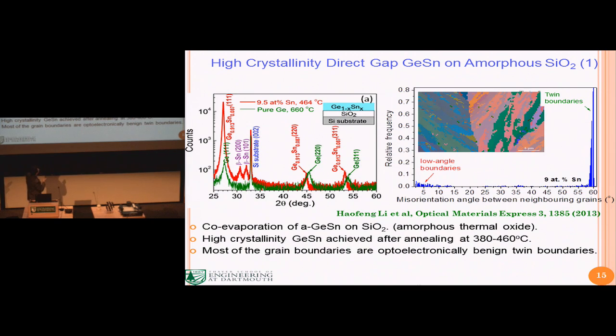And we also did some analysis of the grains. So this is basically using electron backscatter diffraction. Each of these different colors of pieces means an individual grain. The scale bar here is about 5 microns. You can see you can get grain sizes about 10 microns long and a few microns wide, compared to the film thickness of only about 300 nanometers. Usually in semiconductor films, if you get a grain size similar to the thickness, that's already considered pretty good. But this one is far, far exceeding the thickness direction, by orders of magnitude. So that's a very nice crystallization process.